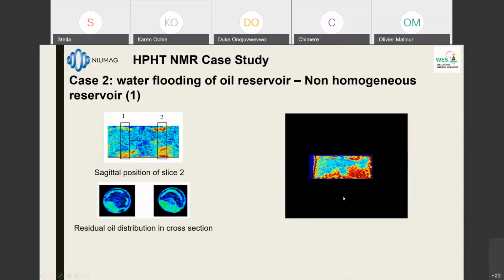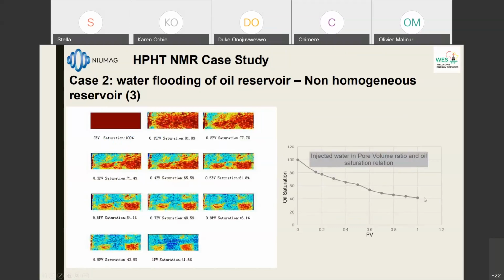Okay, and this is on one place, and you see the patches are remaining. Okay, so just playing the animation a second time. This case here shows us that at the end, when we will have finished injecting this full pore volume inside the core, the saturation is staying around 41.6%. So much more residual oil in that particular case than when we had the homogeneous sandstone.